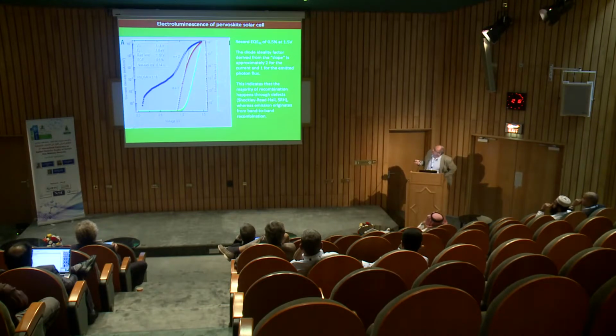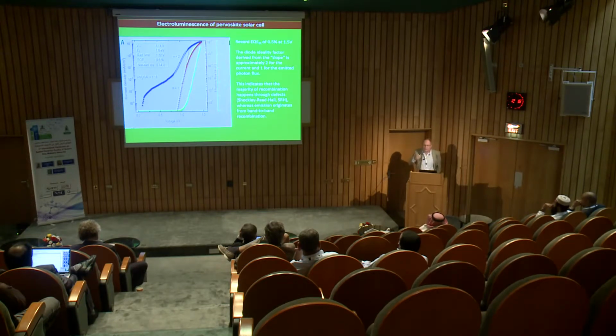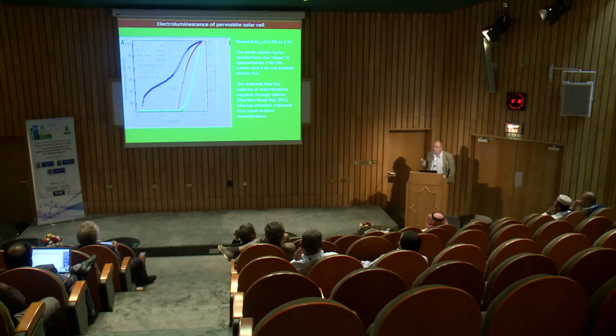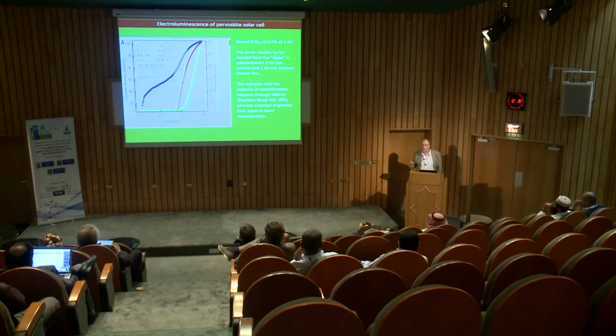This is a bit of a complex diagram, but it shows you that the green one is the focus: it's the luminescence at an applied potential. If we applied 1.5 volts here, we have an external quantum yield of electroluminescence of about 0.5%. And that is sensationally high, actually. For organic solar cells, it's normally 10 to the minus 6 or something. So to have 0.5% we think is a record for this kind of hybrid organic-inorganic solar cell. It also means that this material is also explored for light-emitting diodes and so on.